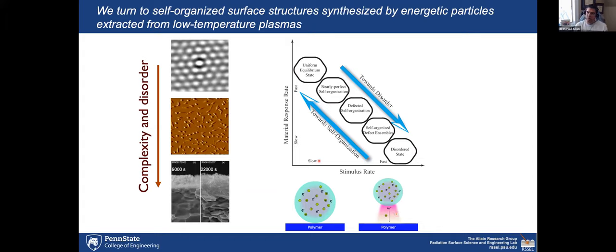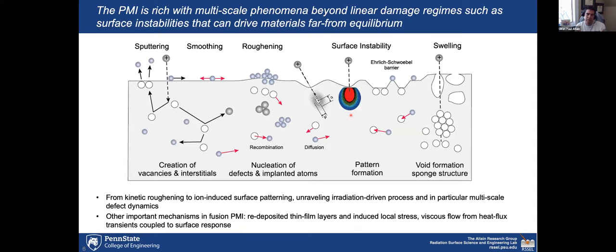And typically when you hear about energetic particles and plasmas, you think about potential damage that can be introduced to your material. But we actually focus on the balance of the stimulus rate to the material response rate so that we can reach metastable phases where eventually we can get self-organized structures where we manipulate the defect in such a way that these atoms can self-organize, and eventually we can design these materials. Now, I won't delve into all the details that are involved in ion surface interactions.